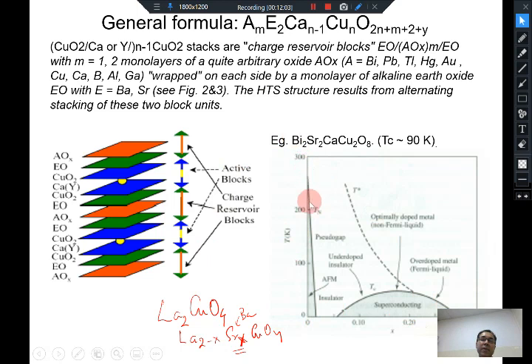Okay, and what you see is that what this line represents is the Néel temperature, because this is an antiferromagnet. It has a Néel temperature. So as you increase the doping concentration, what you find is that the Néel temperature of this parent compound starts decreasing, which means that the long range order in your high temperature superconductor is slowly shrinking, or the ordering temperature is going to lower and lower temperature as you dope the system. Beyond a certain doping concentration, you find that the system loses its long range antiferromagnetic order.